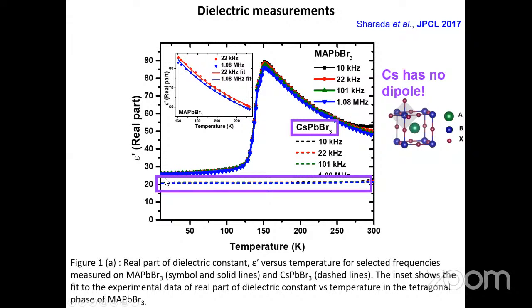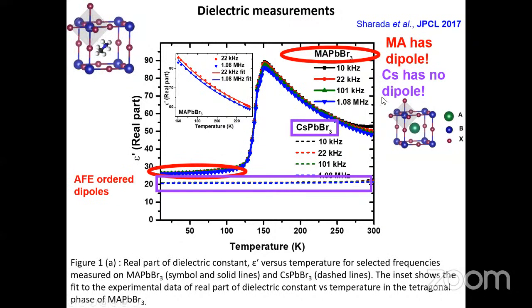It's almost temperature independent, frequency independent, with different colors showing the frequency dependence right here. So if dipoles don't contribute to the dielectric constant, I expect this behavior. Then I look at my compound, MAPbBr3, where MA has a large dipole. At low temperature, where I know they're antiferroelectrically ordered, which means the dipoles will not contribute to the dielectric constant, I find it looks like the cesium analog.